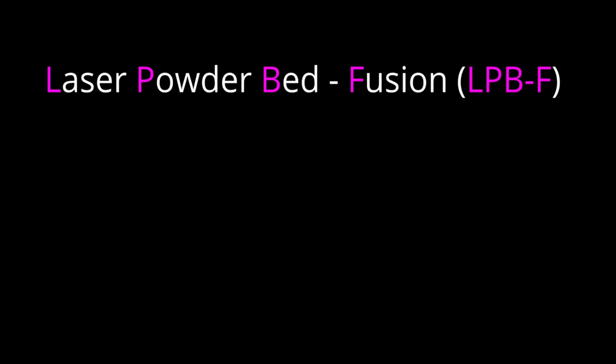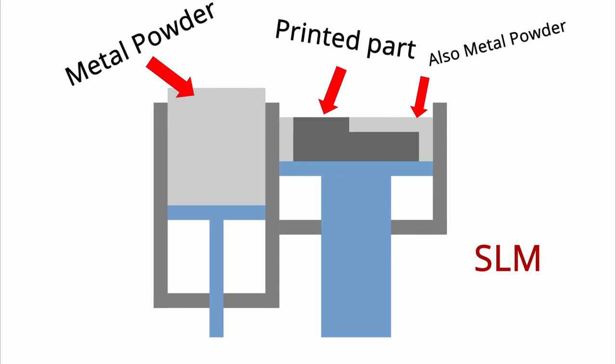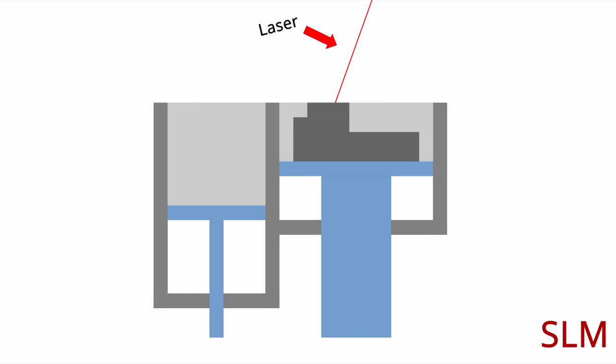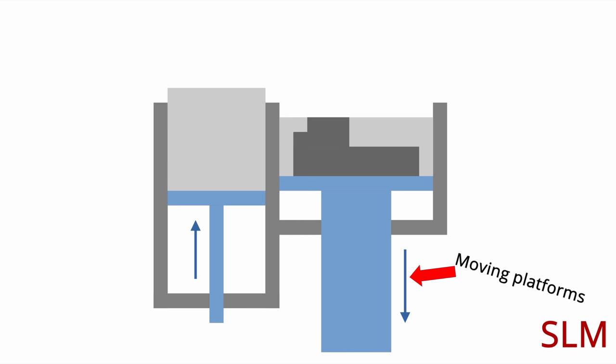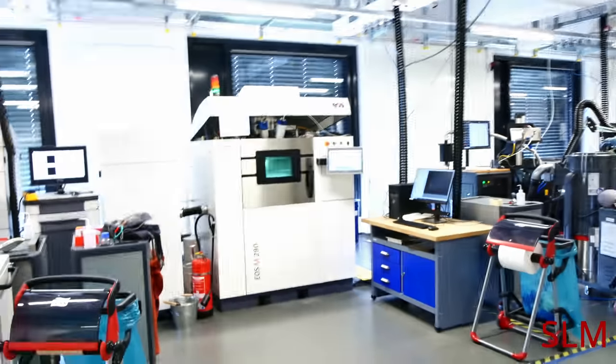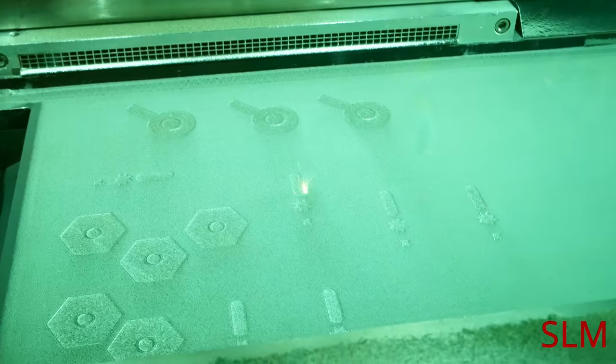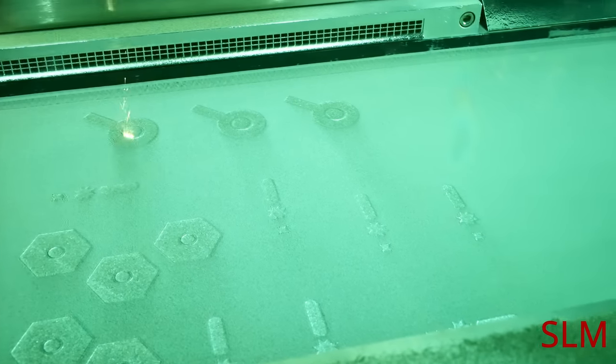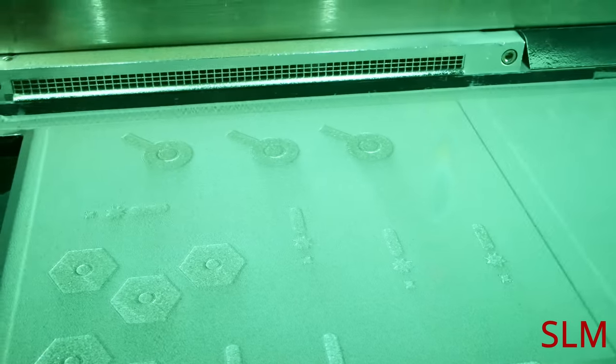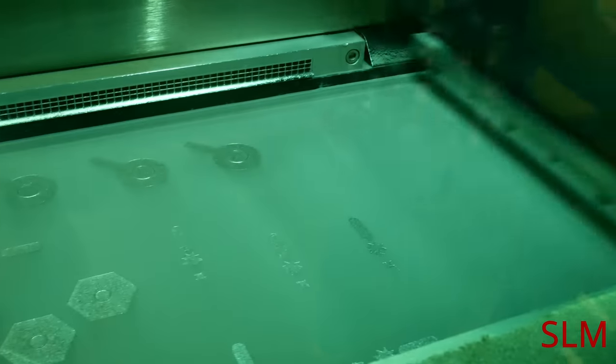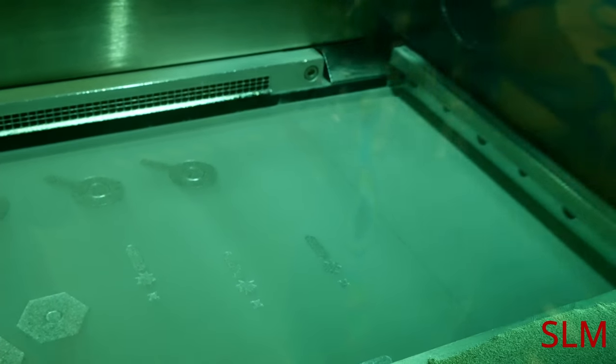We are going to be using the Laser Powder Bed Fusion, also known as SLM 3D printing. Imagine that this is an SLM 3D printer. The way it works is that a very thin layer of powder is first drawn across the already printed part. Then the laser goes over the powder and melts it in specific areas. Finally, the build platform is lowered together with the printed part and the excess powder. Following this, the cycle repeats until the part is finished. If you're doing this in the real world it looks something like this: the laser goes over the already printed parts, then the build platform goes down a little bit, the re-coater re-coats a thin layer of powder over the already existing parts, and finally the laser goes over it again, creating an infinite cycle.